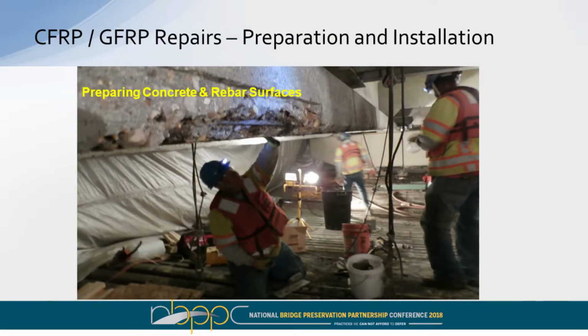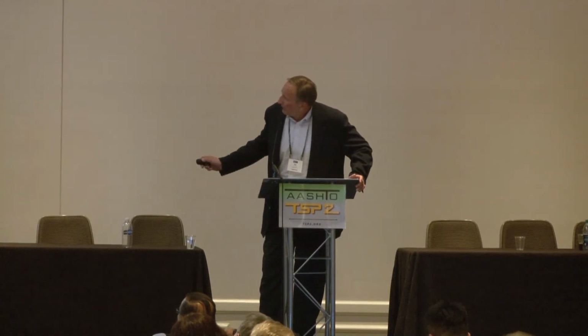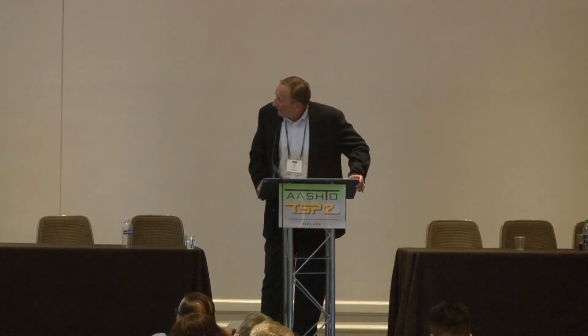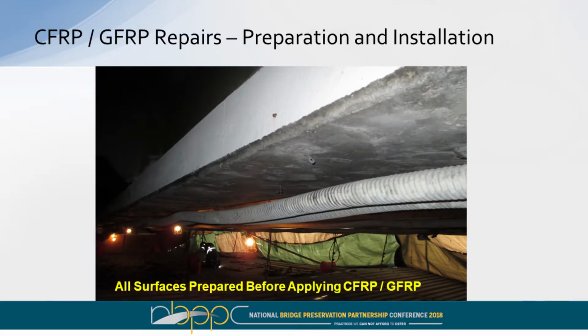So with that shop drawing in play and approved and us moving forward, we now move into final preparation of the concrete surfaces. You can see here, we've finally removed a lot of the poor concrete. We've squared off some of the repair areas. We've removed a lot of the concrete materials that were surrounding some of the corroded steel, cleaned up the steel, obviously paying very close attention to the pre-stressed strands. And of course, from there, we continue to refine that, and then we come up with a finished surface that we feel comfortable with as far as placing the carbon fiber and glass fiber materials on.